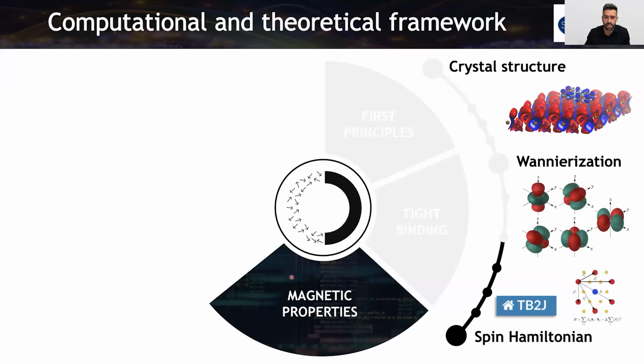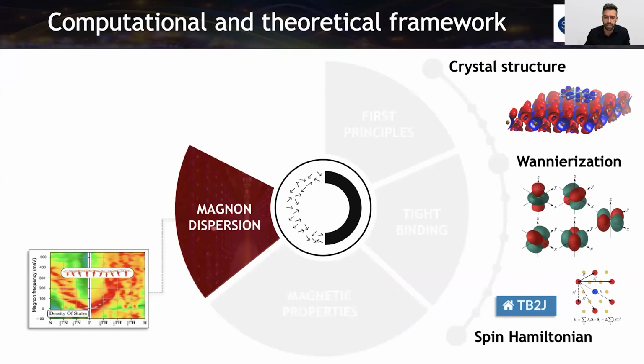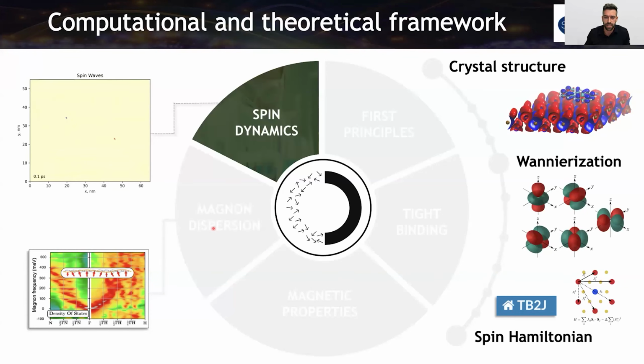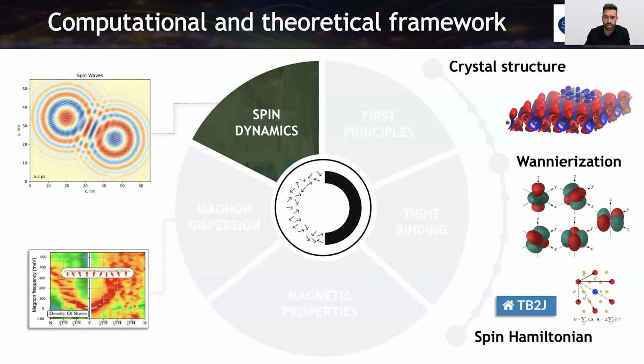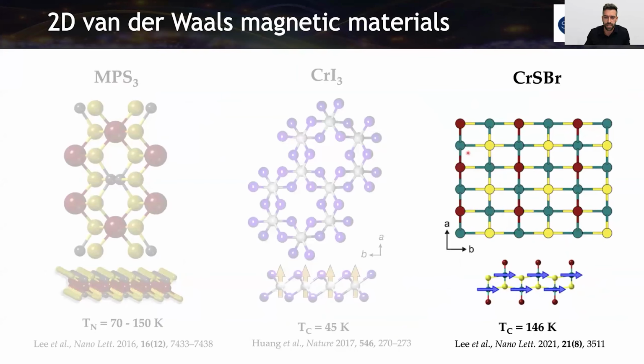So we calculate magnetic properties. Then we can calculate magnon dispersion, and also if we apply Landau-Lifshitz-Gilbert theory, we can simulate the real-time, real space propagation of the spin wave, so the spin dynamics. I will start with the studies in chromium sulfur bromide.